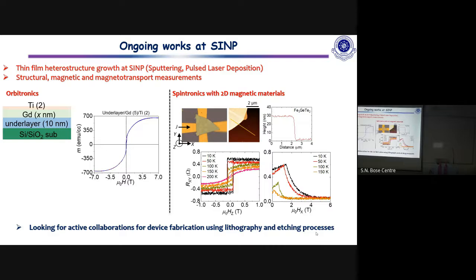Actually, the signal you are measuring is neither resistivity nor the usual Hall in the common sense. Yes, if it has a component of magnetization in that direction. So if you reverse the current in the other direction, what do you get? You get the same. We didn't check that. No, actually, if it is due to a simple resistive part, then it would be symmetric, where one can reverse the magnetic field and it will usually cancel. That was spin anisotropic texture and also reversible.